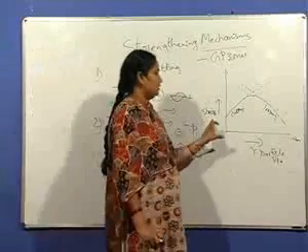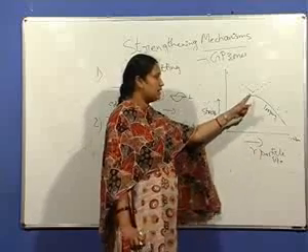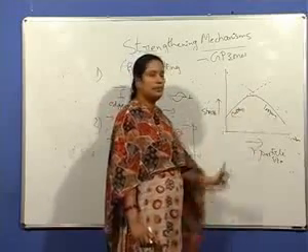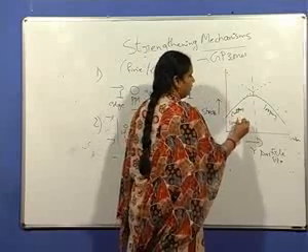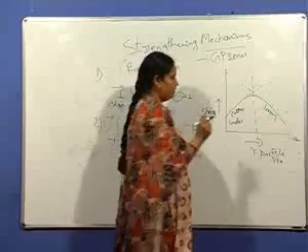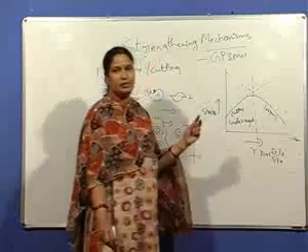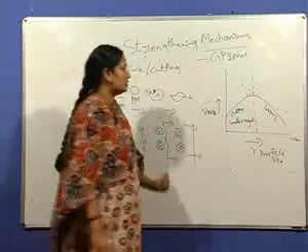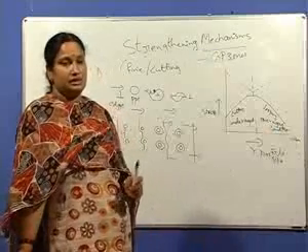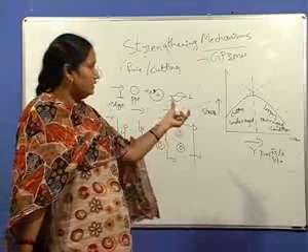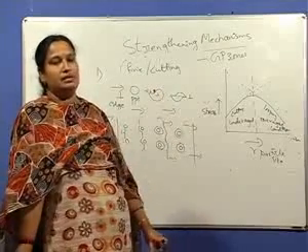The cutting mechanism operates when the particles are very, very fine in size, that is in the underaged condition, and the looping mechanism operates when the particles are coarser. So this is the overaged condition. Dispersion strengthening comes under the overaged condition of the precipitation hardenable alloys.